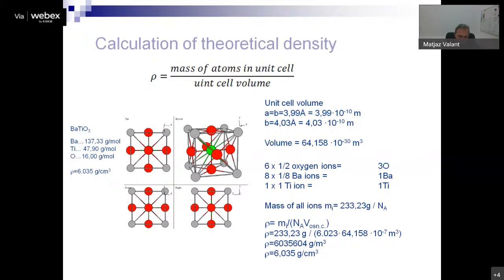There's another very useful tool. This was used in old times mainly, when they were trying to determine the exact crystal structure and stoichiometry of a material. They grew a single crystal and compared its density with the theoretically calculated density. And if the numbers were very close together, then they were sure the structure was correctly determined. Otherwise, that was an indication of some error in the structural determination.